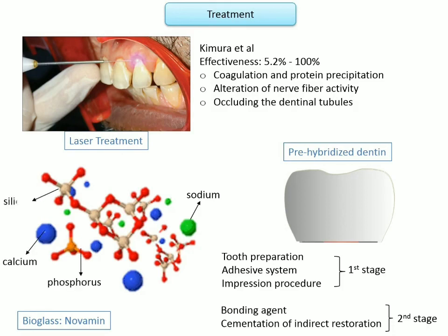Bioglass. So, Novamin, the active ingredient in DenShield Bioglass agent, is a bioactive glass that has been ground into fine particulate with a median size of less than 20 micrometers and is composed of calcium, phosphorus, sodium, and silicon. When exposed to an aqueous environment, it releases calcium and phosphate ions. A layer is formed through several reactions starting from nucleation sites and finally crystallizes into hydroxycarbonate apatite, which is equivalent to hydroxyapatite in biological behavior. It's acid resistant, so it offers long-term relief, thus alleviating hypersensitivity.